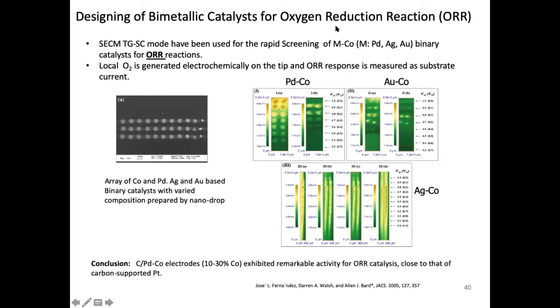But to analyze each and every catalyst, suppose we have to analyze 30 compositions, it's going to take 6 months. What his group has done is put various small spots of various compositions of cobalt with various metals. You can see here about 30 spots. And they analyzed them basically in one go. From this current response, they could identify that this particular composition of 10 to 30% cobalt is very active for the ORR reaction. So in one go, I can determine the activity of various compositions of this catalyst.